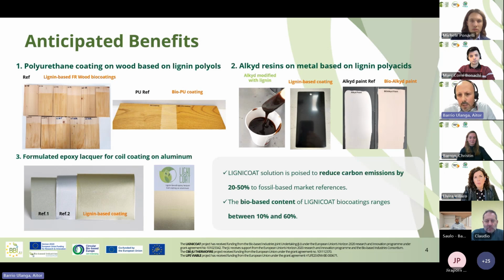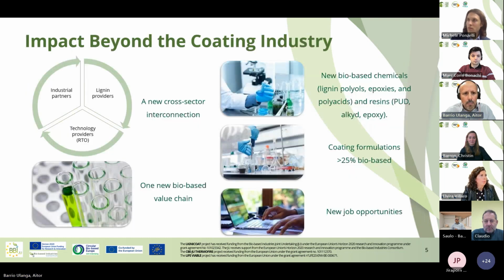The main goal is the reduction of carbon emissions by 20 to 50%, and also increase, as commented before, the bio content. We are between 10 and 60 depending on the technology. So the impact is the creation of a new cross sector, because the lignin currently is not used in the production of resins for coatings. A new bio-based value chain based on this raw material and the final applications.